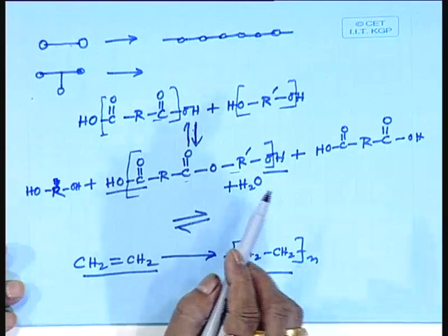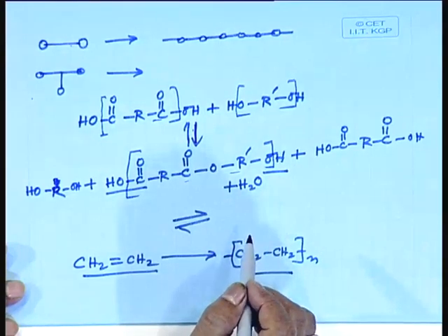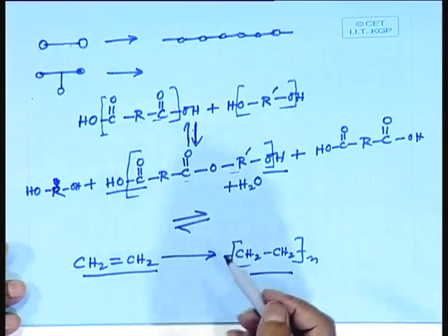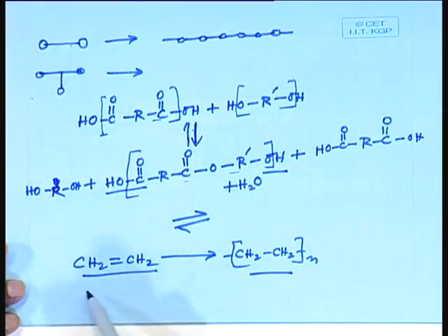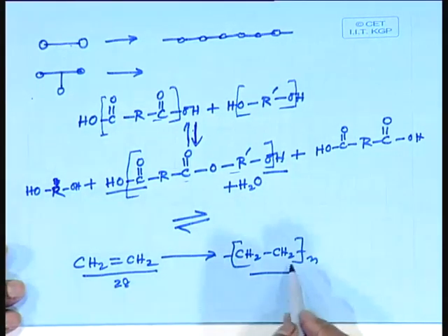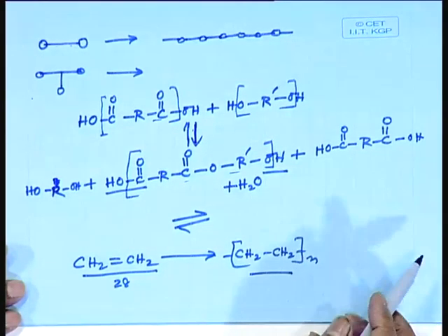Okay. So, in order to calculate the molecular weight of a polymer, how can you calculate it in case of a condensation polymer and in case of an addition chain polymer? Here you see the calculation of molecular weight of an addition chain polymer, it is very easy. Molecular weight of the monomer is here 28, here n number of units of mass 28 are present in the polymer chain.